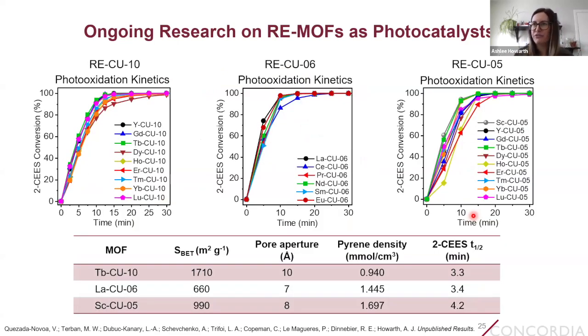And so we wanted to look at the photooxidation kinetics, and compare it for all three of these different MOFs to continue to gain a deeper understanding of what structural features really dictate faster half-lives or better catalysts. If we take a look at the best MOF in each series, so that's terbium Cu10, lanthanum Cu06, and scandium Cu05, and we look at the pore apertures and pyrene densities, we see that in general, all of these MOFs have what appears to be a nice balance between pore aperture size and pyrene density. And they also all have fairly fast half-lives, although with some differences amongst them.